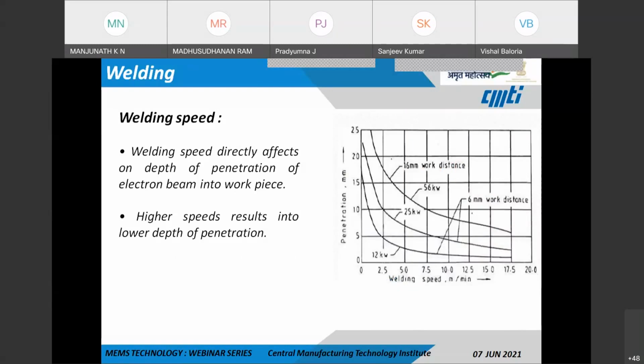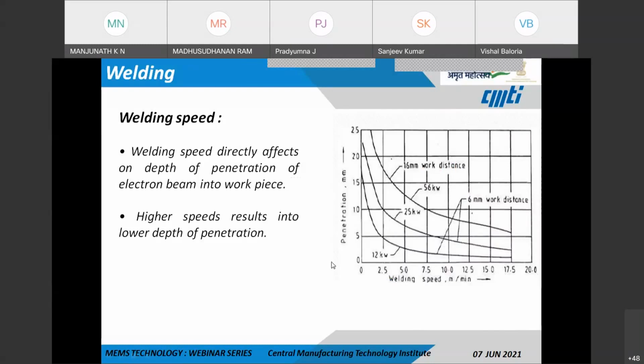And yet another parameter is the welding speed. The welding speed directly affects the depth of penetration of the electron beam into the workpiece. Higher speeds result in lower depth of penetration, wherein this graph clearly shows that even with a higher accelerating voltage and a closer distance of the workpiece, with higher welding speed, the depth of penetration attained is very less, and vice versa, where at lower accelerating voltage and high distance between the workpiece and with lesser weld speed, the depth of penetration achieved is considerably good.